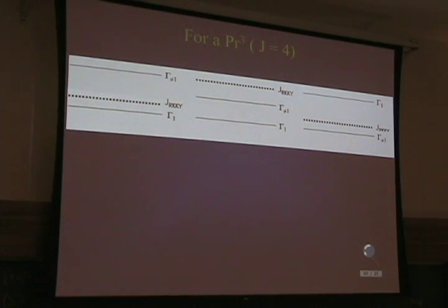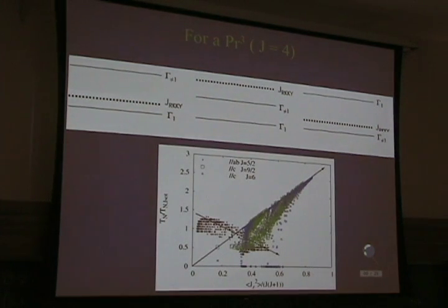Or alternatively, if you tune your crystal field parameter, change one ion for another, keeping the same RKKY interaction, you can drive non-magnetic to magnetic, right? If you substitute one ion, change the potential, invert the wave function, now you have an RKKY interaction and a magnetic state, you can order just by tuning the crystal field. But that's not obvious for the Kramers ones, for the cerium ones, right? But that model has shown that it may happen.